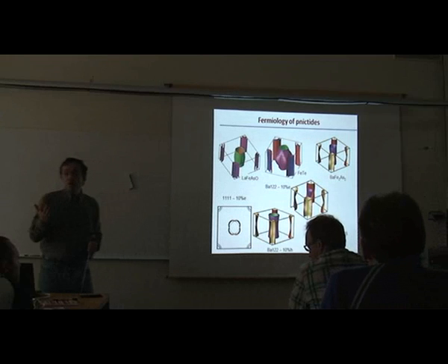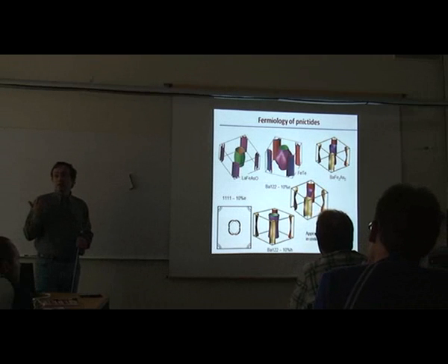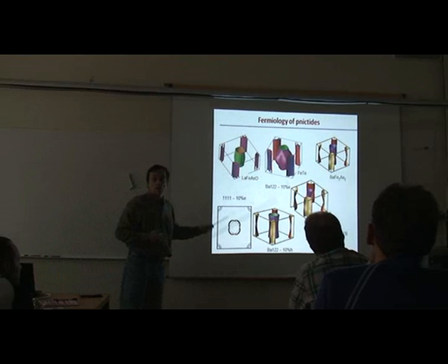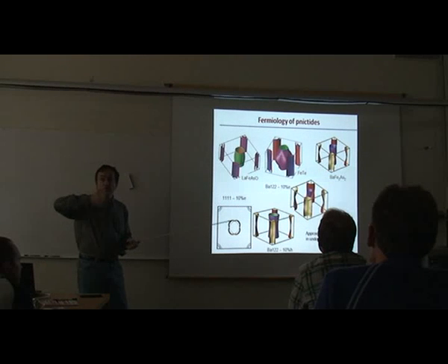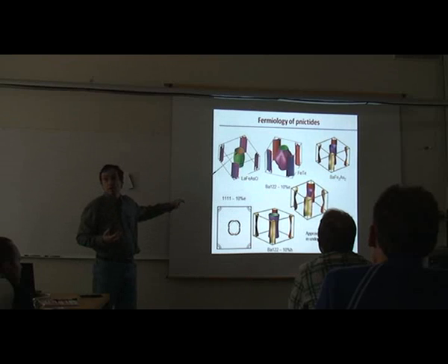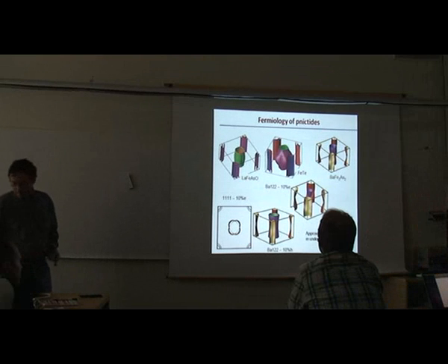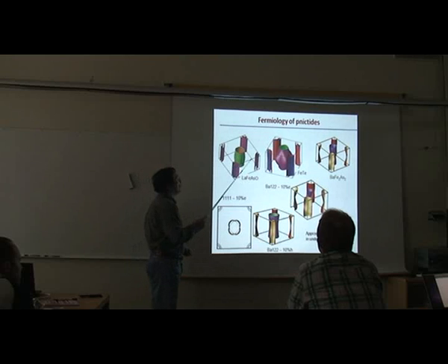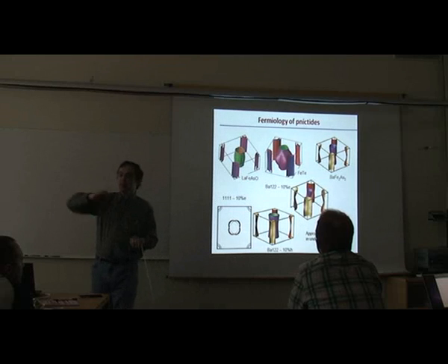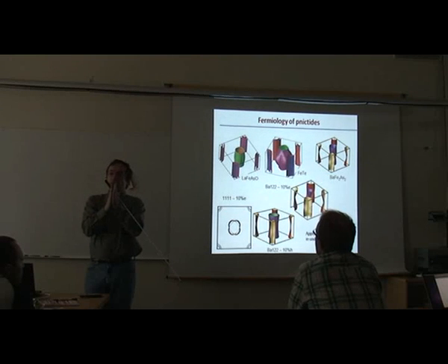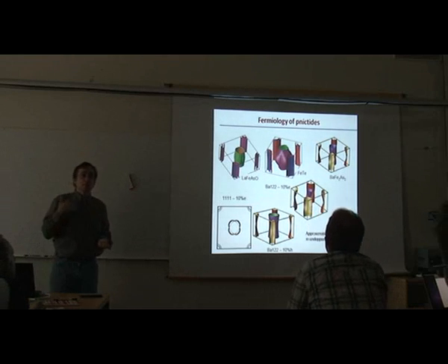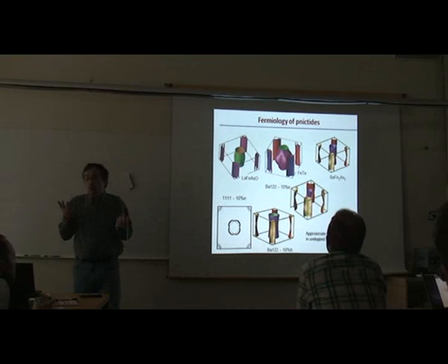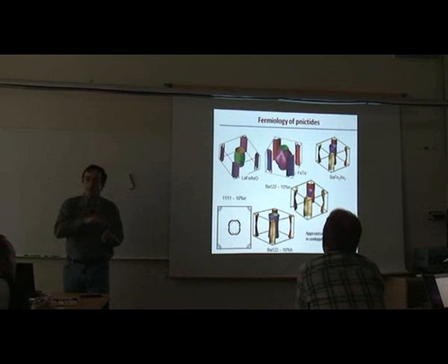They look almost quasi two-dimensional, but the materials are not two-dimensional. They're actually only weakly anisotropic. Those are results of ab initio calculations. So you can see that there are 3 concentric cylindrical surfaces here and 2 here, 5 bands. For certain dopings, you can move this part to the middle, and it will be what people call nesting, when the surfaces coincide. In which case you can expect structural instabilities and spin density wave instabilities, and many people believe that this nesting is what is driving this entire antiferromagnetic transition in the underdoped state.